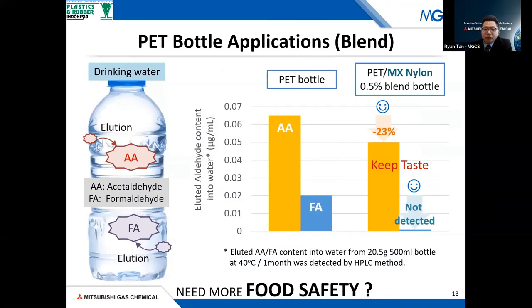Other considerations: I believe most participants would have also drunk some weird tasting mineral water or bottled water before. While we can easily brush it off as the standard taste of mineral or bottled drinking water, more often than not, this taste change is normally due to the presence of acetaldehyde, more commonly known as AA. With the use of MX nylon in very small dosage, at about 0.5%, as compared to just now when I was talking about 5%, you are able to get a 23% reduction in the AA content.